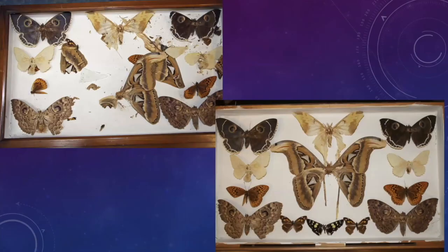So for something like this top left, where the glass has obviously fallen in, crashed on top of these large moths, and damaged them very, very badly indeed, you can actually do a lot of repair work using this type of tissue. In some cases, these have already suffered damage from pests and so forth, and there's not much you can do about that, but at least the majority of the specimens are now back in good condition. Goodness knows what happened to the atlas moth abdomen. There was no sign of it whatsoever, unfortunately.